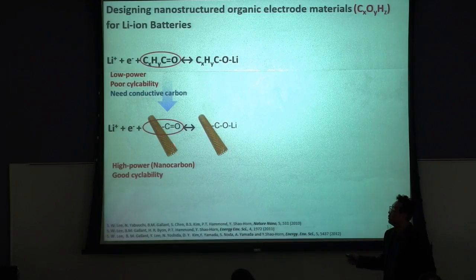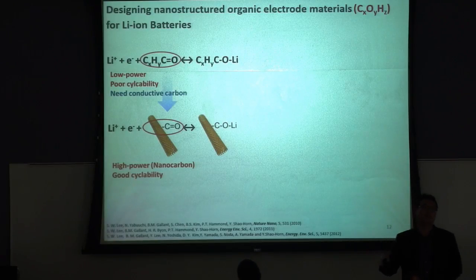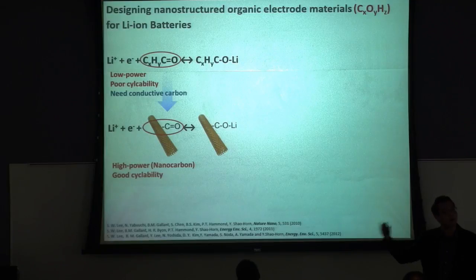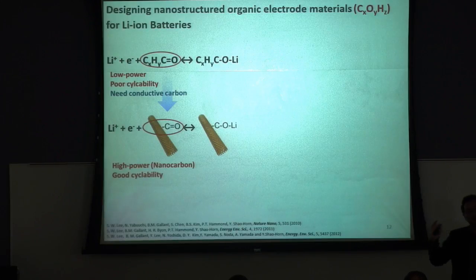So our strategy is to incorporate the oxygen functional groups on a conductive carbon matrix, such as carbon nanotubes. This is a schematic of carbon nanotubes. We are trying to chemically incorporate oxygen functional groups on top of the carbon nanotube via covalent bonds. Then the carbon nanotube can support high electrical conductivity, so this can improve the power performance. And these molecules are now attached on the surface of the carbon via covalent bonds, so we don't need to worry about the dissolution of the organic molecule.